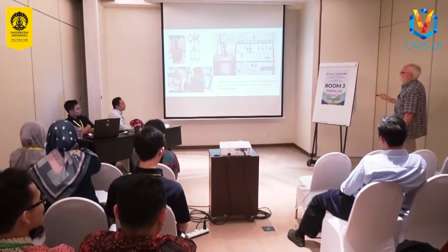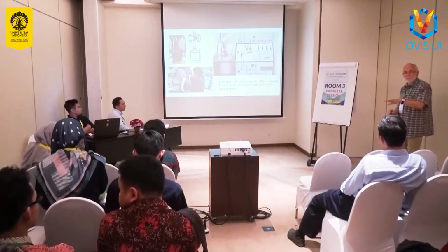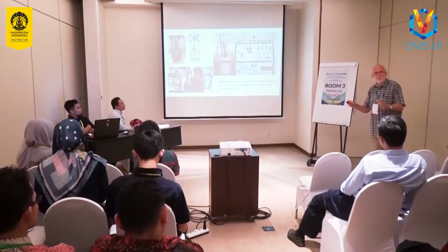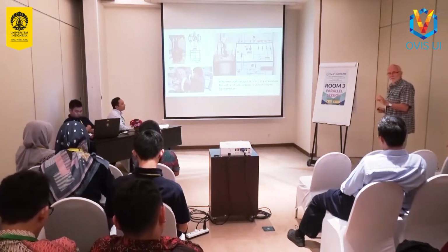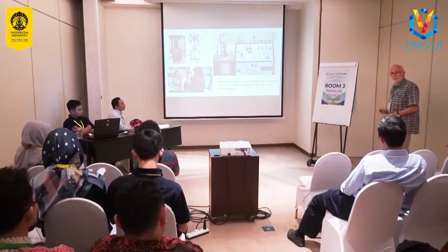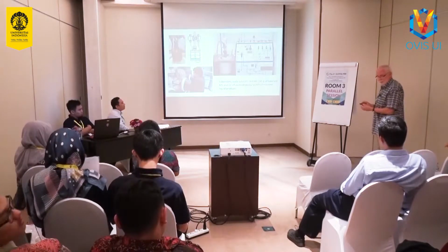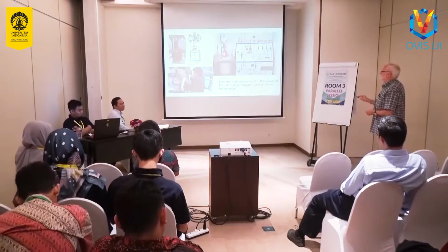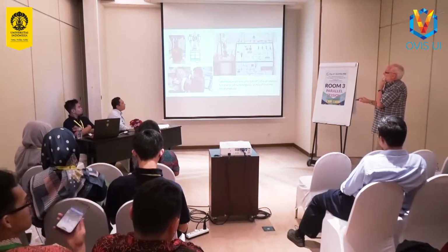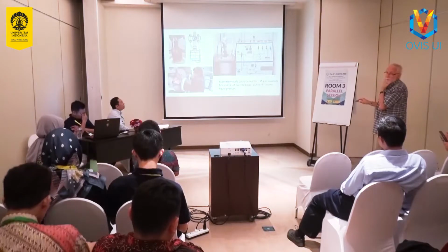Now, when we first started doing this, our hope was that we could take this reactor and stick it immediately in the neutron spectrometer. And we can do, but it's made of stainless steel to withstand the pressure and the temperature. And so the stainless steel is relatively thick. That means that we lose a lot of intensity if we have the sample in the stainless steel reactor. So what we've done instead is a rather cumbersome procedure, which Antok here got very good at, which is we take this reactor, seal it off, put it into a glove box, unload it, and put the contents into an aluminium can instead of a stainless steel can, so to do the neutron spectroscopy.